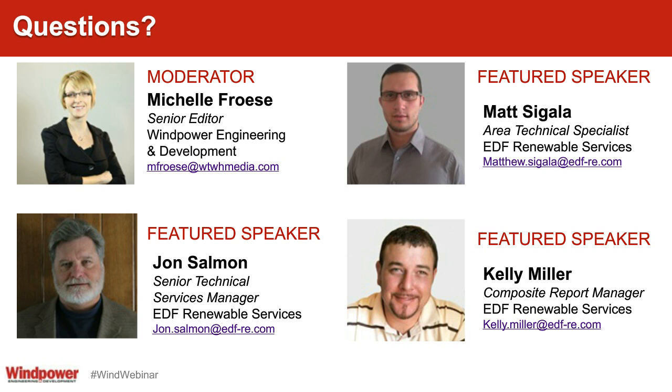For sure. Another question, I think for you, John, is why is moisture ingestion a problem, and why aren't blades waterproof? I imagine that would be the ideal world. Well, they're intended to be, and they start out being waterproof. They typically have a top coat on them that is very moisture resistant. But obviously, that's the point of this whole discussion: these blades require maintenance, and that top coat can break down either through cracking or erosion or whatever. And the moisture then has a path to the internal part of the blade, and that is a problem for a couple of reasons.